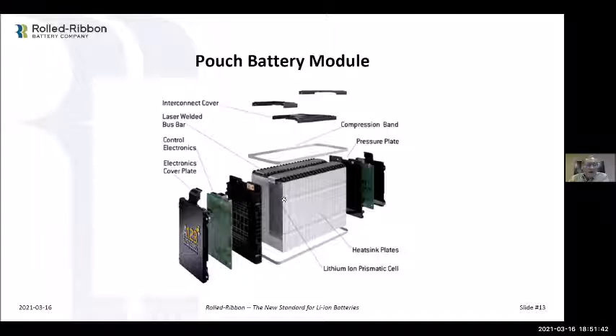The other thing that happens when you have a pouch cell is you charge and discharge it, lithium cells expand and contract. And so when you have those sheets, you have to have a space gap. Well, that air gap is an insulator, and you can't really put anything against it to get the heat out. So the heat sink plates provide some nominal amount of cooling, but it's really de minimis. And then they armor the soft pouches.